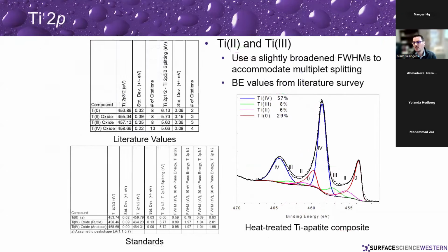Similarly, for something like titanium, we can do the same sorts of things when we have tables of all the different values for the splitting values, for where the different oxidation state species will be, and how to fit that asymmetric peak shape. And again, we can say, okay, we've got so much metal, so much titanium 2, titanium 3, and how much titanium 4 oxide we have present.